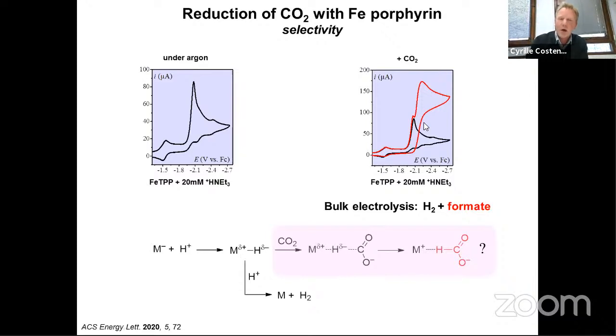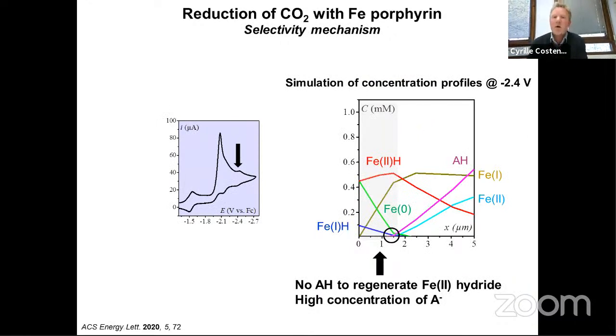Is it possible? Actually, this is not what's going on. And it's possible to show that by just looking at the concentration profile at this position of the CV, for example. Because you have consumed all the acid in the diffusion reaction layer, as you can see from this total catalysis wave, this means that in the diffusion reaction layer, you don't have acid anymore. So here is the distance from the electrode, and you can see that there is no more acid. You just have hydride, okay?